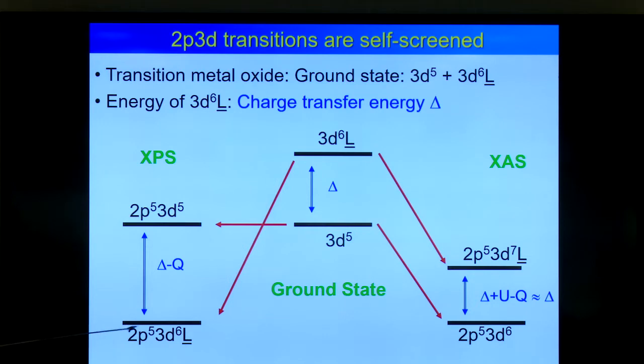Now actually you need more, so now you need at least 3 configurations, maybe 4, because they are very high in energy there, but they all come down here. So that's the difference between X-ray absorption and photoemission calculation. So the theory is the same, but the states which are needed are completely different.